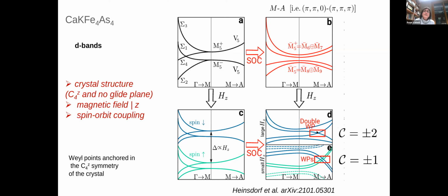Yes. So the double Weyl point is, in this case, Weyl points that come because the bands have non-degeneracy, while in the Dirac points we have degenerate bands touching. And in this case, we have bands of the same polarization, but it's the angular momentum which is opposite. And this gives rise to these double Weyl points, which means that in the direction perpendicular to z, along kx and ky, I'm going to have a quadratic band touching, while along the kz direction, I'm going to have a linear band touching, like in the single Weyl points. I don't know whether this was clear.